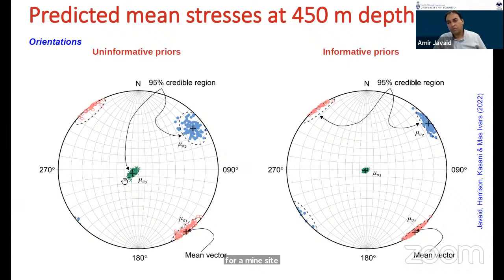Okay, so first of all, most of us will tend to think that the rock mass at the Forsmark site, since it's a monolithic granite, is probably not heterogeneous, but I differ. It's probably more heterogeneous in the top few 100 meters, where we have more intense fracturing, and that causes more perturbation, especially for the stresses. Now, the dilemma here is that if we look at this data again, without any lines on it, you can clearly notice that we have more stress measurements at shallower depth, which is more perturbed and more heterogeneous, and fewer stress measurements at deeper depths, which is considered to be more homogeneous. So it's one issue.